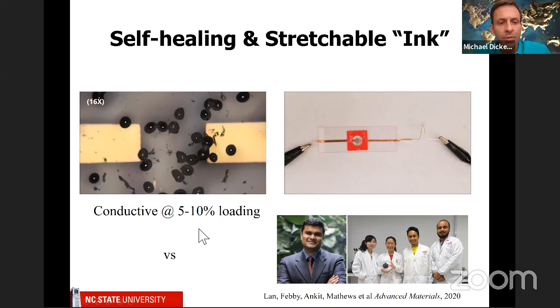Instead, we applied a voltage across these electrodes and we used that to assemble the particles. And the really cool thing is because they're liquid particles, they merge together into a continuous chain. To give you some appreciation, we're able to make microwires using 5 to 10% weight loading of the liquid metal, whereas composites tend to require 80 or 90% to get percolation. So this is in some ways not all that surprising, but where it gets really cool is that